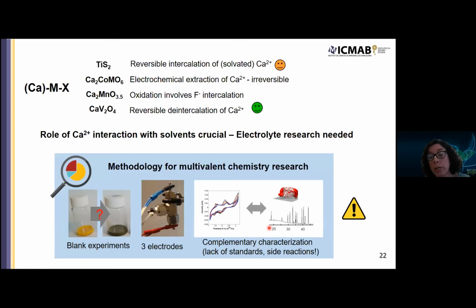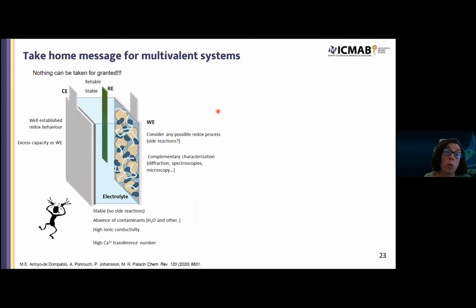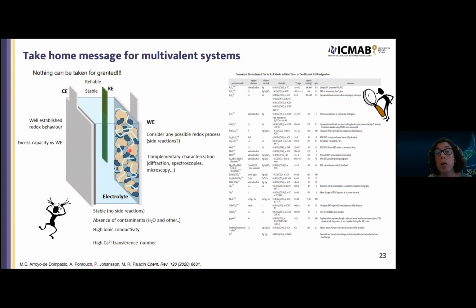The anode also has issues. There can be many side reactions going on, as you saw, for instance, here with fluoride intercalation. So one has to be very careful when interpreting results. So nothing can be taken for granted. You need to make sure that your electrochemical setup is reliable, and there are many issues that one should look at. And also for the positive electrode materials, care has to be exercised when interpreting just an electrochemical response.